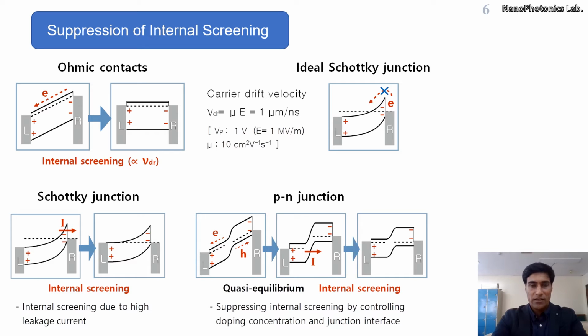This is the basic concept. Ideally, there is a Schottky barrier junction. When a Schottky barrier junction is created, there is a Schottky barrier height which prevents the flow of electrons, and ideally there should not be screening. In the semiconductor, there are free electrons, and those free electrons screen the piezoelectric potential. In reality, the interfaces have defects and there is a leakage current, and because of that leakage current the piezoelectric potential can be screened by the free carriers. So in our group, we have investigated the Schottky junction, the homojunction, and the PN junction, and our conclusion is that with a well-grown pn-homojunction and a well-optimized resistivity of the p-GaN shell, we can suppress the internal screening. So I will discuss it in my coming slides.